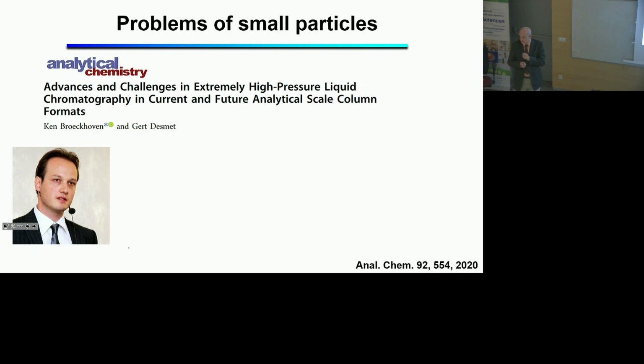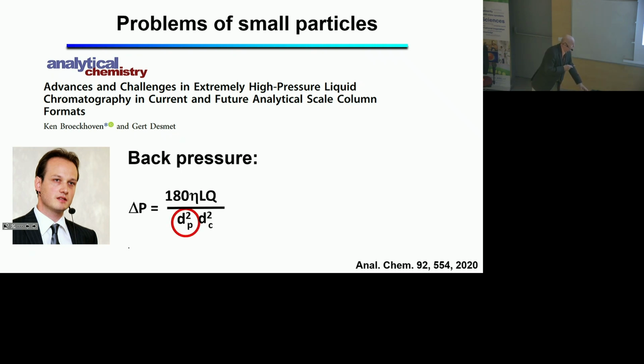However, there is nothing like a free lunch. And this man, Ken Broeckhoven, used this equation to demonstrate that there is a problem with friction heat. You know, the pressure we are using is energy. And this energy has to be somehow dissipated. And the energy is changing to a change in the temperature inside. And well, changing temperature during the run means that we have a system that is not homogeneous. You know? We have to get rid of the heat, and this is a problem. So decreasing the size of the particles also has this negative issue that has to be dealt with. So we cannot go too far down simply because we would run into trouble with the friction heat.